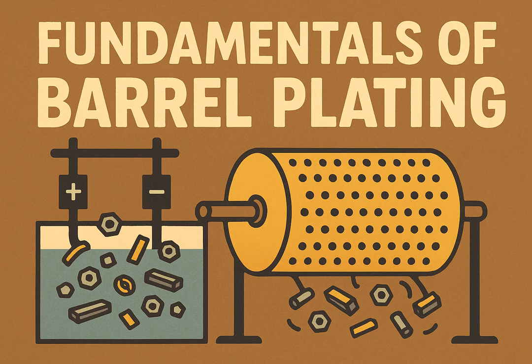Clean, clean, clean. The guide suggests cleaning with dish soap, abrasive cleaners like Cameo, or even briefly using reverse electroplating, where the object is made the anode to strip away contaminants. They also caution that some metals, notably stainless steel and aluminum, are tricky to plate directly onto and may require a copper underplate first to ensure good adhesion, even at the DIY level.